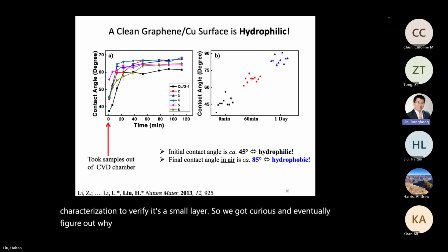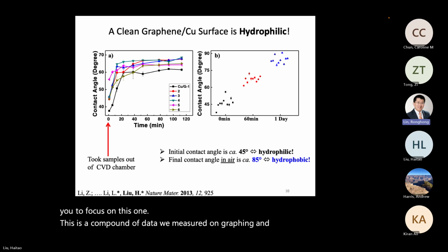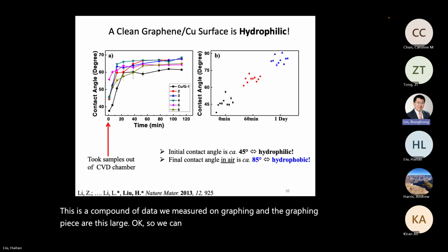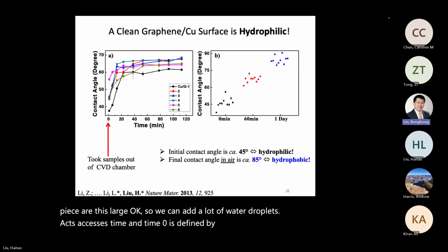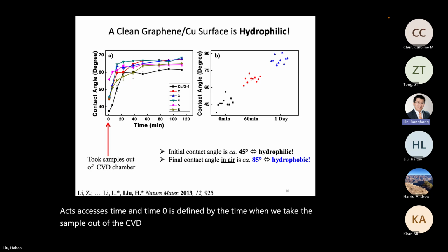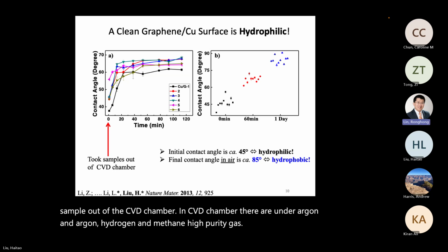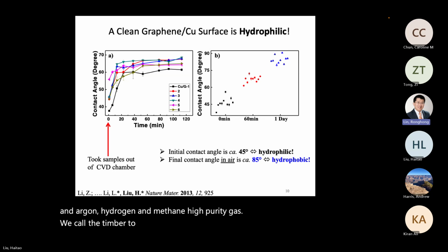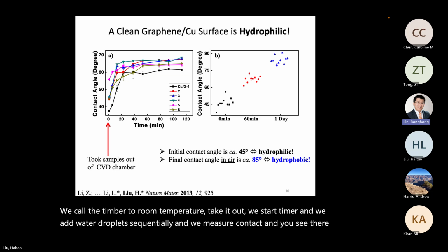So this is probably the most important piece of data. I want you to focus on this one. This is the contact angle data we measured on graphene, and the graphene pieces are this large. So we can add a lot of water droplets. X-axis is time, and time zero is defined by the time when we take the sample out of the CVD chamber. In the CVD chamber, there are argon, hydrogen, and methane high purity gas. We cool the chamber to room temperature, take it out, we start the timer, and we add water droplets sequentially, and we measure contact angle. And you see there are 6 different samples.